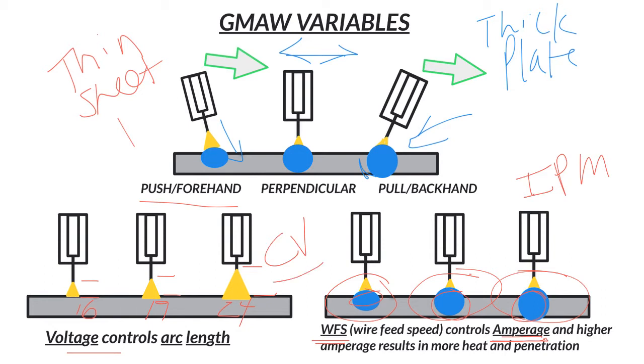So the voltage, whatever you set it at, let's say you go to 19 volts and you get a little bit closer, and maybe that voltage actually drops a little bit just because you're closer. It doesn't need the pressure there to maintain the arc. And anytime we talk about power, if voltage goes up, amperage goes down, and if voltage goes down, amperage goes up.